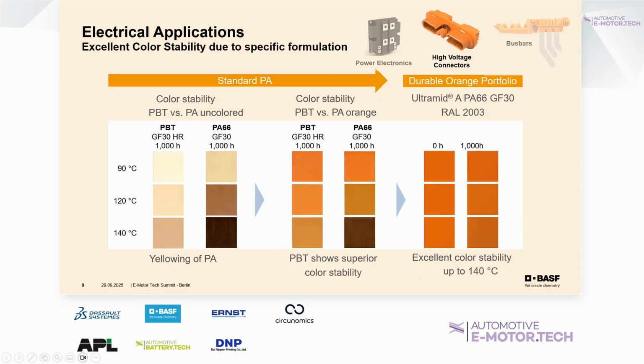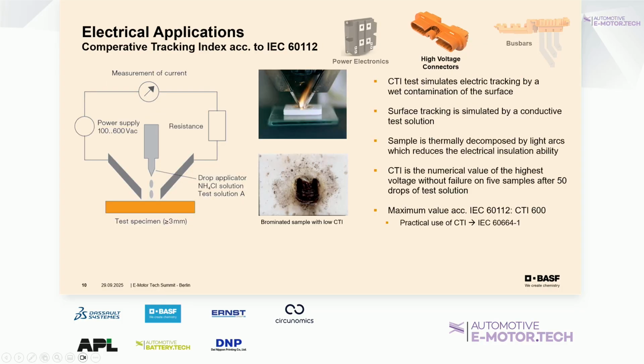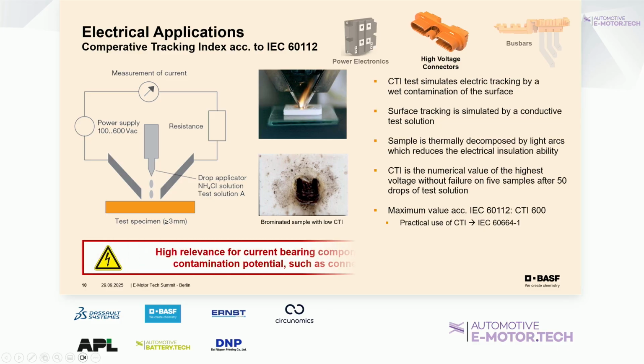The third example I have here regarding electrical applications is the, sorry, I missed one important test, the CTI test. I already had a nice discussion today with one of the colleagues here. The CTI test is typically a test which simulates a kind of tracking by a wet surface. So you typically have these two electrodes, a kind of dripping liquid, and you test several voltages. And at the end of the day, you don't want to have a sample looking like this here. So you want to make sure that there is no real arc, what you see here. It's especially relevant, like I mentioned, for connectors or high voltage components.